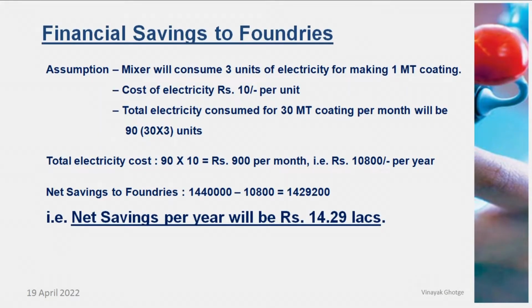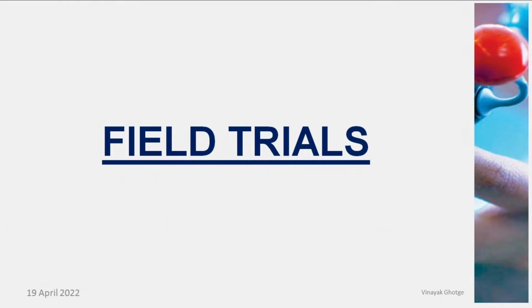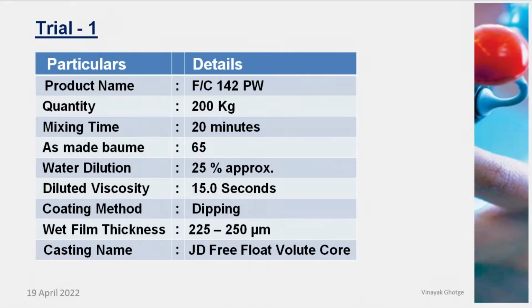Benefits will be substantial. Now I'll go through the field trials which we have taken, so that it can give you an idea of how versatile the product is. This trial was taken in one of the foundries where the casting is a small volute core. It is a foundry producing automotive castings, turbocharger castings, and the trial was made with about 200 kg of coating. The application viscosity was about 15 seconds, and the application process was dipping.